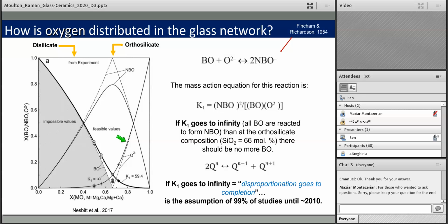This depolymerization reaction here was first shown just based on stoichiometric considerations, with no evidence to back it up, back in 1954. And using the law of mass action, we can create an equilibrium constant, K1: the products, with the coefficients as the superscripts, divided by the reactants on the left-hand side of the equation. If we turn to how that looks on the graph for a moment, we have 0% metal oxide added. In this example, Nesbitt et al. used magnesium, calcium, etc. And you can have 100% metal oxide or 100% silica down here. We've seen that 100% silica has just Q4 species, and all the tetrahedra are connected to one another. So we have 100% bridging oxygen, and along the y-axis is the mole fraction of the different oxygen species.